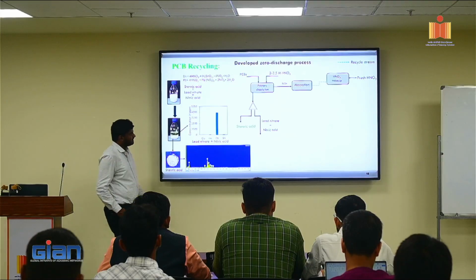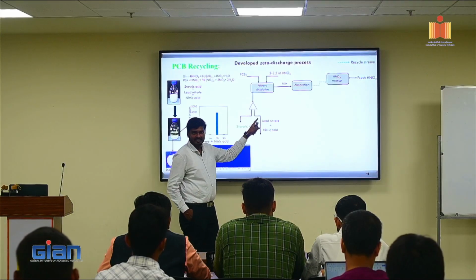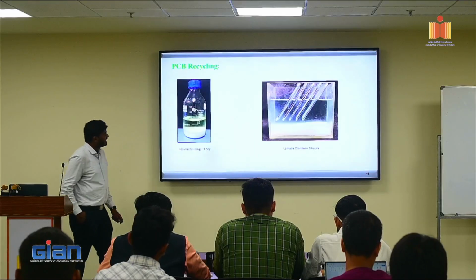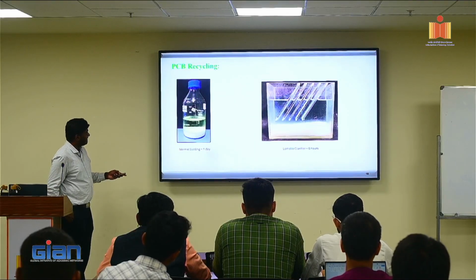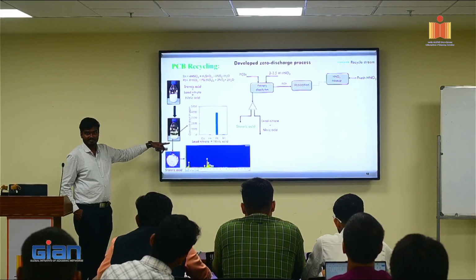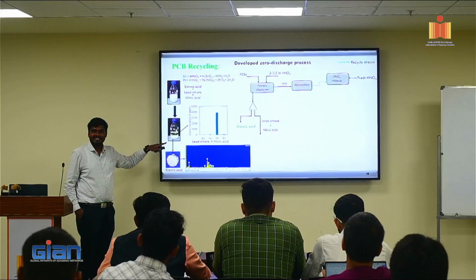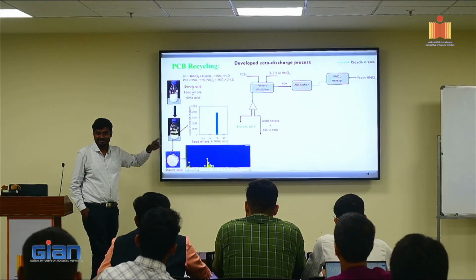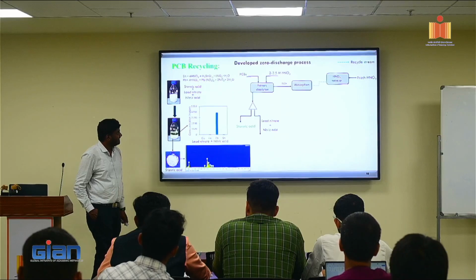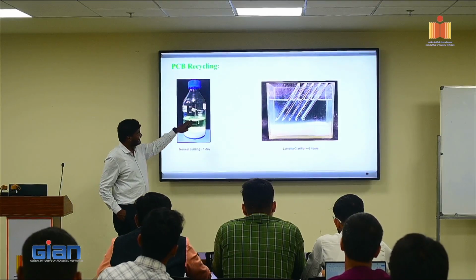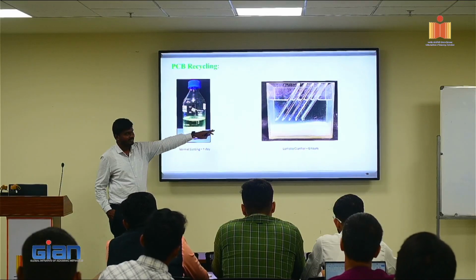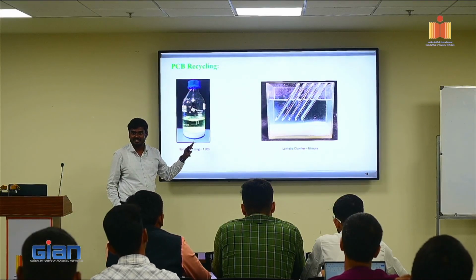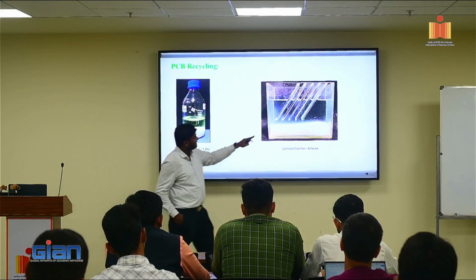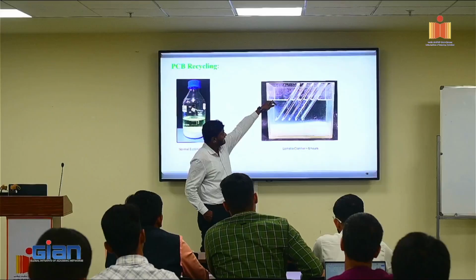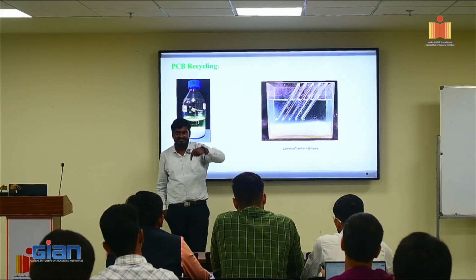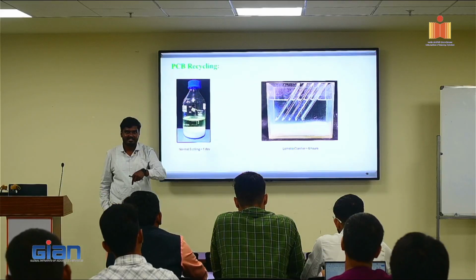Now the next focus was on this stream where we get lead nitrate and nitric acid. But before this, one more thing. Here I told you it takes 24 hours to settle, and I don't want slow rates. To enhance the settling rate, we modified this. Rather than using normal batch settling, we developed something called a lamella clarifier. It's already there in industrial scales also. Typically, with these inclined slides, the solid particles touch them and slide, which is faster than gravity settling.